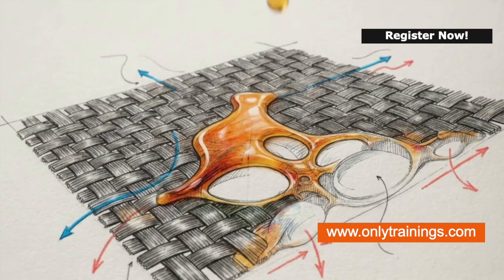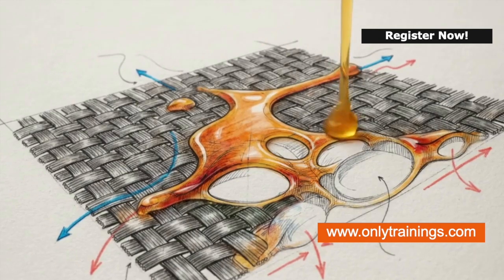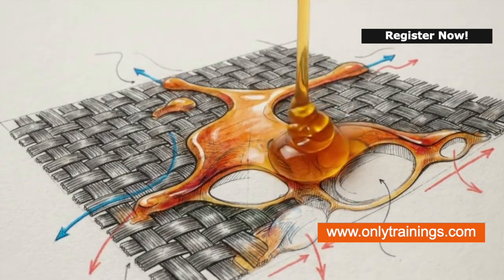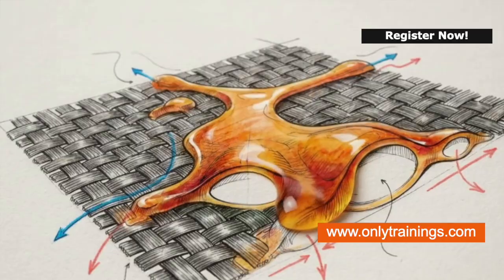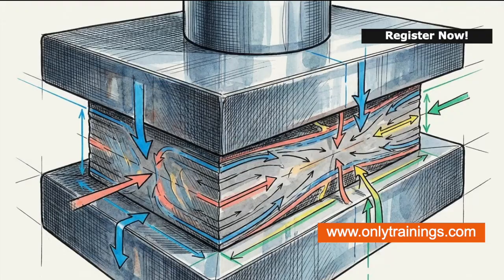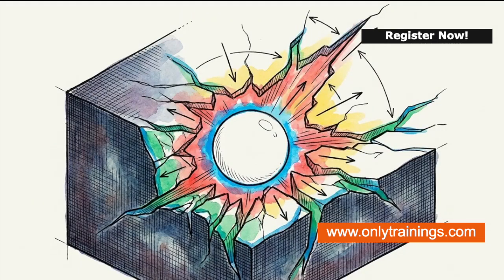The viscous resin fails to penetrate the fiber bundles. This leaves localized dry spots and generates microscopic voids trapped deep within the composite structure. Under physical load, these internal voids act as extreme stress concentrators. A microscopic gap becomes the exact point where the structural part cracks and fails.